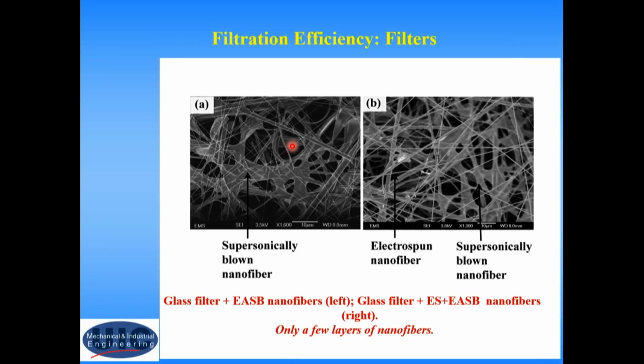So essentially what we did, we took the basic commercial filter, which I believe is cellulose or something trivial and commercial, with big cells, about 50 micron. On top of that, we deposited regular electrospun nanofibers, and then on top of that, we deposited a layer of supersonically blown nanofibers. So in this SEM image you see the whole structure together. Some big fibers in the background are the supporting filter. Then you see electrospun nanofibers, which are intermediate in size. And then you see the thinnest ones, the closest to you. These are supersonically blown, 20 to 50 nanometers.